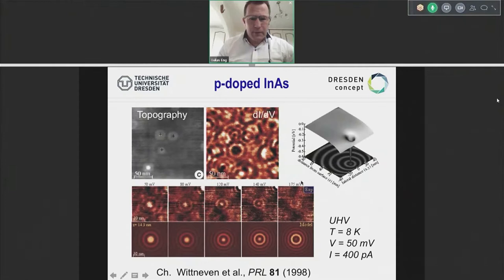Please note the following. We have here a higher energy, 175 millivolts. And if you look at the density of these rings here, as compared to 50 millivolts, you nicely see that the wavelength has increased. So that's exactly what you can do. You say, well, I'm looking at any material that scatters like a scattering wave, by measuring the impact at the sample surface.